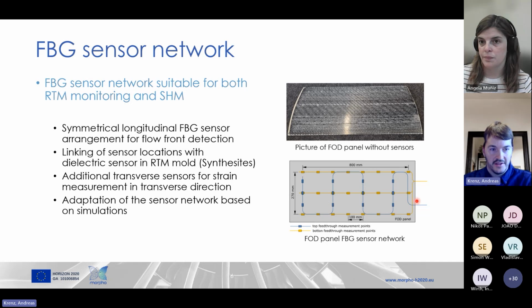We had some additional transverse sensors integrated in, for example, this array for additional strain measurement in this transverse direction. And we adapted the sensor network based on simulation results, for example, having some additional sensors on the outer edge areas where some peaks of stresses occur during impacts.